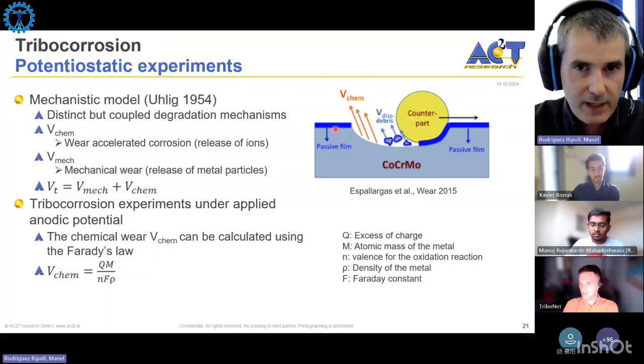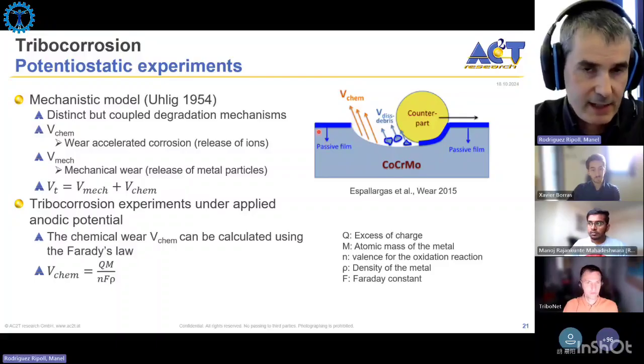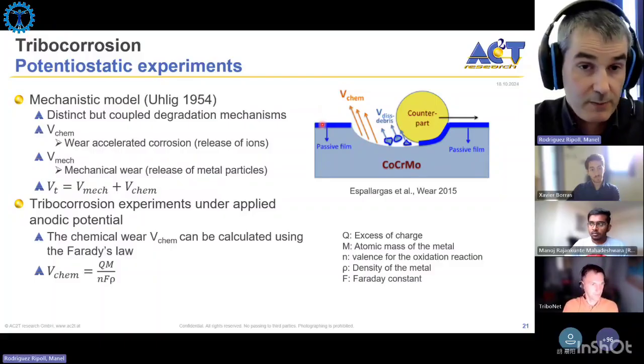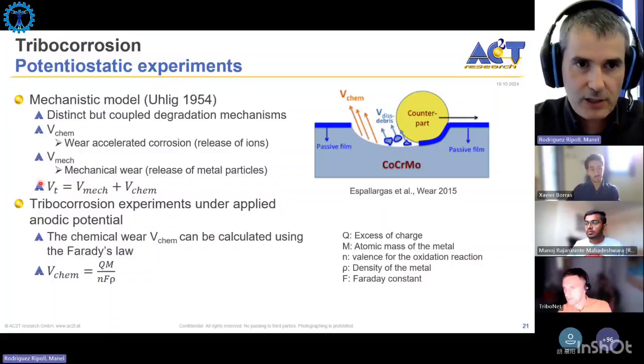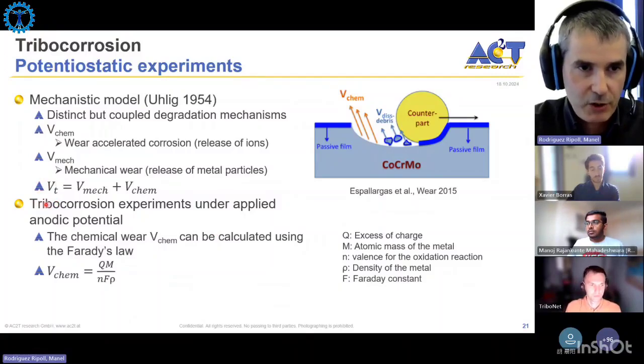And the chemical wear outside the wear scar, we can neglect it, because we have seen that for passive metals, the passive dissolution is very small. And we can assume that most of the chemical wear is coming from the depassivated area here in the wear track. And in these potentiostatic experiments that I showed under passive applied potentials, basically we can measure the total removed volume at the end of the experiment. So this is the volume that we would measure using profilometry or confocal microscopy.